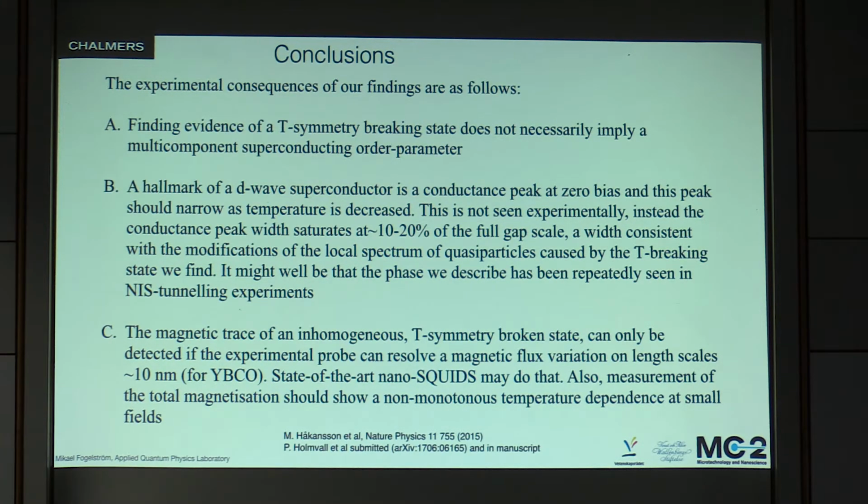Then secondly, I think that the old experimental data that's around on tunneling is actually quite consistent with these findings, in the fact that when you're going down to 20% of TC or so, there's no decrease in the width, which you would expect by just the thermal broadening shrinking, but it's sort of fixed, and it's at a rather large value.